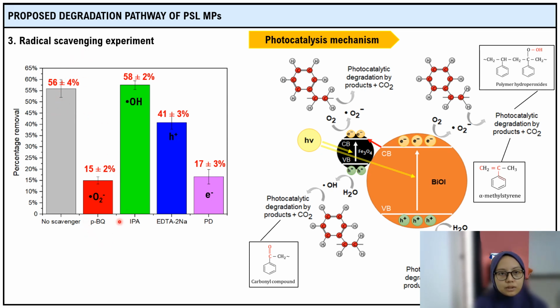However, when parabenzoquinone was added, the percentage removal can only achieve 15%. And when potassium dichromate was added, the percentage removal can only achieve 17%. It can be concluded that superoxide anion and electron are the main active species in degrading the polystyrene microplastics. The polystyrene microplastics were degraded through a photocatalysis mechanism and produce intermediate products such as polymer hydroperoxide, carbonyl compound, and also alpha methylstyrene and carbon dioxide molecules.